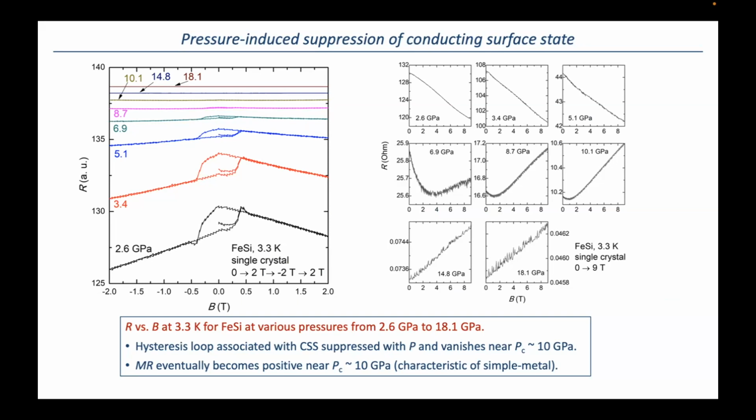And all of this changes again at this pressure of 10 GPa, where you presumably close this Kondo insulator energy gap. If you look at the resistance, you can see that at the lower pressure regions, it's negative and large. When you start to approach this transition, it turns over and becomes positive, and that minimum moves to lower pressures. And then once you're well into the metallic state, it's positive like you might expect for a metal. So I find that to be really interesting.